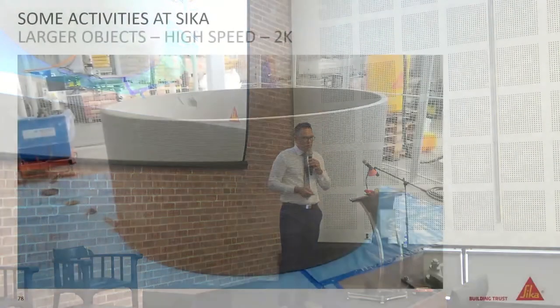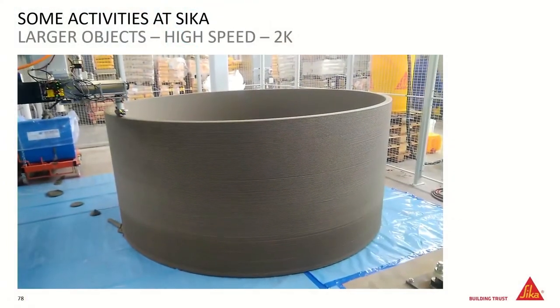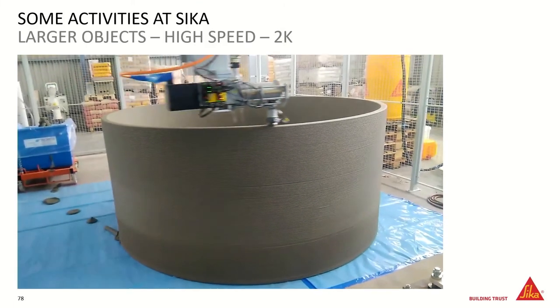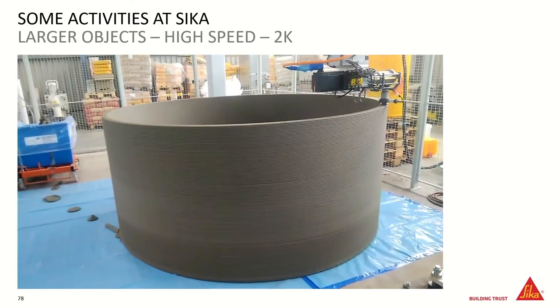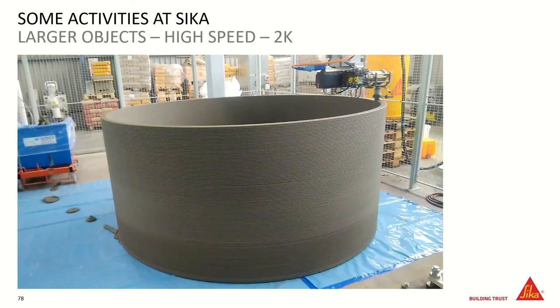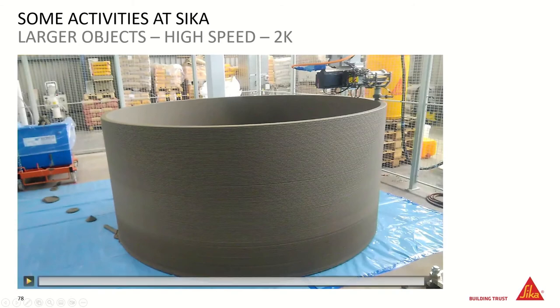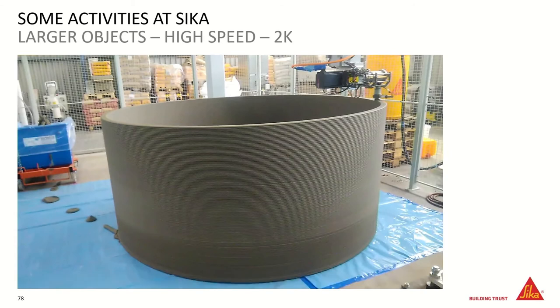So here's a reasonable speed. So with the two-component material, we can print it up to 1 meter, excuse me, 1 meter per second, which is very, very fast. Most one-component material, you will print about 0.25 to 0.3 meters per second. So it's much, much faster. And you can build because you're curing or setting the material as you are printing it.